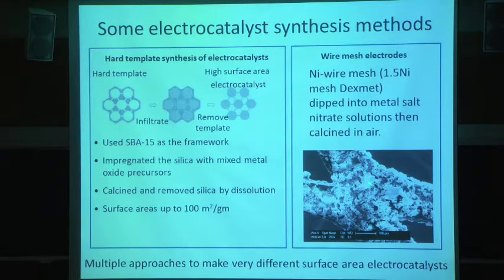And finally, we looked at a metal mesh. So this is looking at the intersection of a metal mesh, which we had dipped in the nitrate salts and then calcined in air. And it has this sort of tree bark look to it. So this mesh looks a lot like what is in your window screen, but it's made out of nickel instead of stainless steel. So we have a pretty broad range of materials, all compositions from pure nickel oxide to pure iron oxide and everything in between.